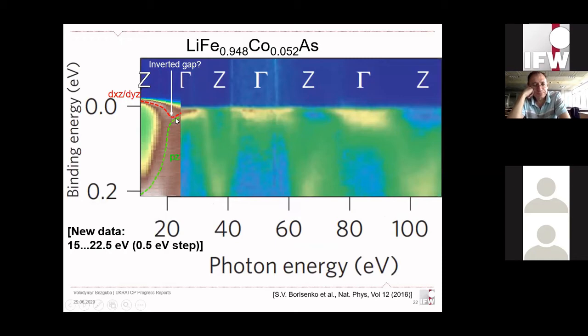First of all, it should be very small. Like I said, from our calculations, we expect it to be on the size of 20 meV. So with renormalization, it gives us like 6 meV. And secondly, it looks like bulk bands dxz, dyz, and pz are so strong that they just crush everything, and you can't see anything here over the intensity. So there is an inverted gap here, but it's not possible to see it.